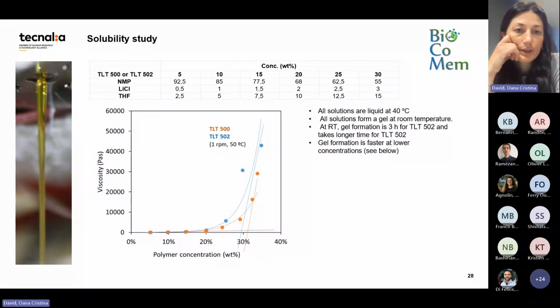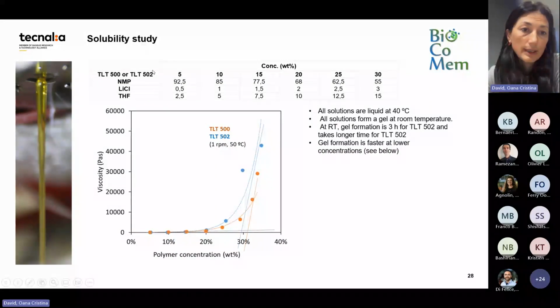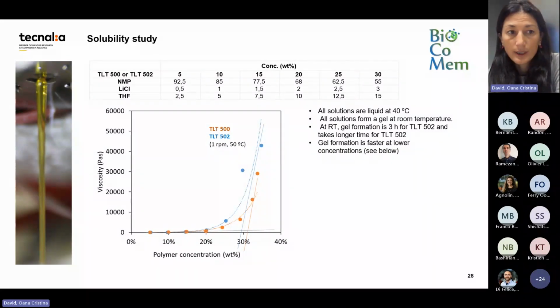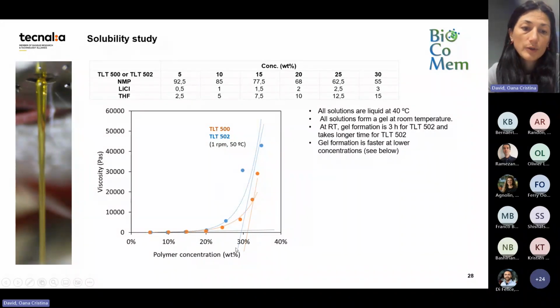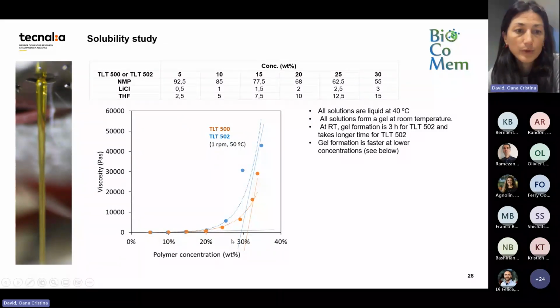So then we started with the scale-up polymers. They were at 10 kilogram scale. We started to do a study of what concentrations of this polymer we should use in the spinning solutions, because we need to form a stable thread. There is a minimum concentration that we need to use for this thread to maintain itself in the air gap. And this is determined based on this kind of graphical representation where we have different concentrations, and we check from which point the viscosity starts to increase exponentially. We have determined that the good concentration is about 30%.